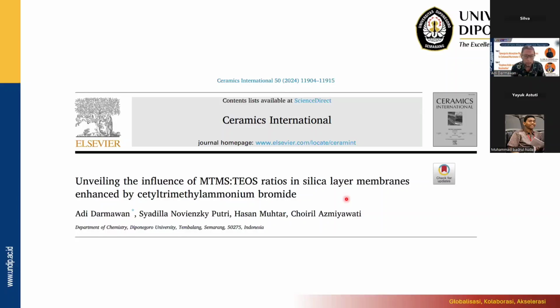When I came back to Indonesia, there was no equipment to do research on gas separation, so I moved to desalination. The problem of the silica layer is that silica has OH groups, which can easily interact with water. The interaction between the OH groups and water can destroy the silica structure and reduce the performance. So we had to find an idea to make the silica structure resist water interaction.